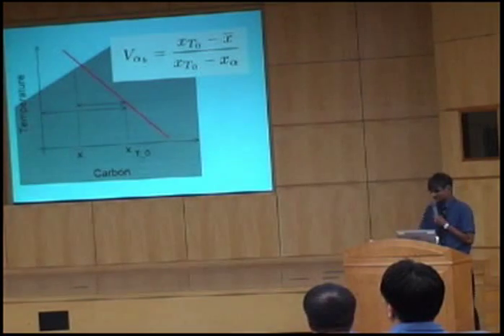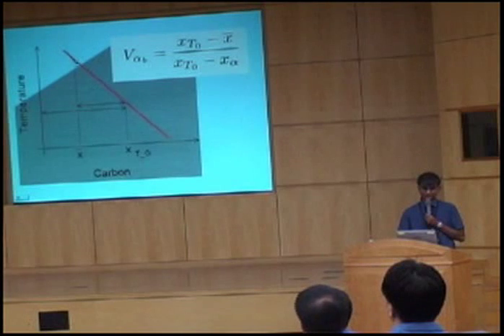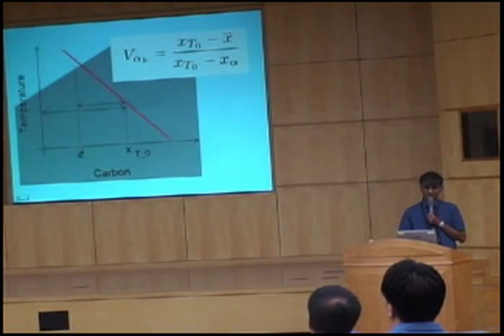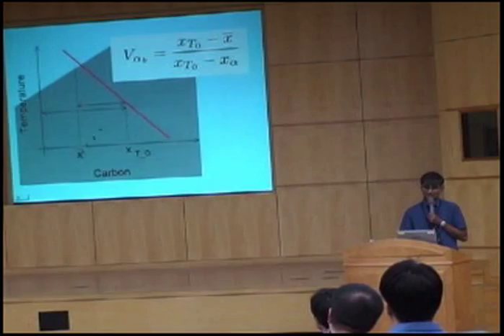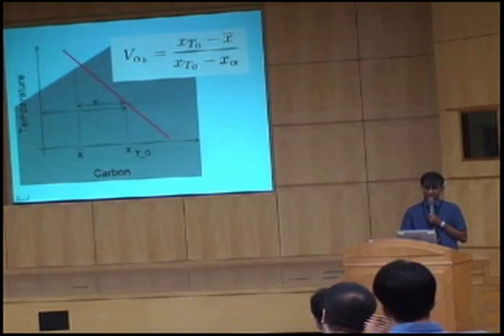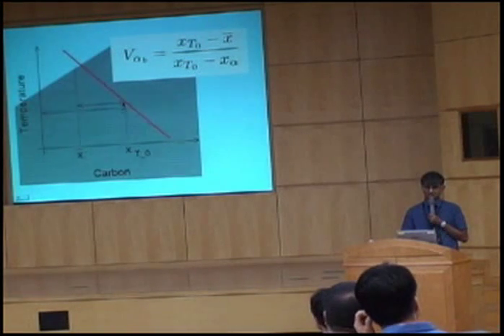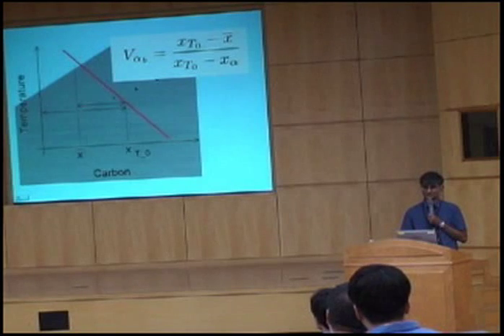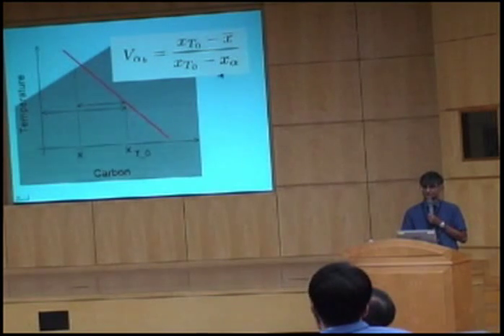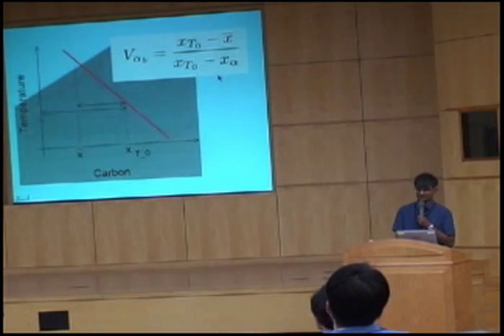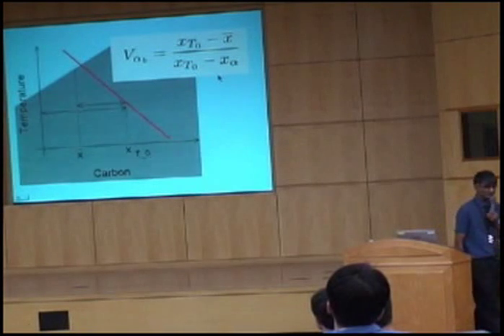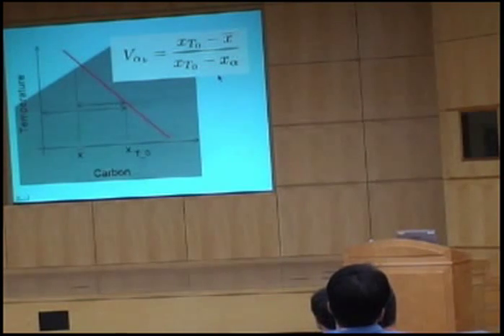So, this is our T0 curve here. This is the average composition of our steel, okay, in terms of carbon. And the volume fraction of bainite that we can get is given by this distance divided by this distance, because you can take the carbon concentration of ferrite to be zero. Okay? Solubility of carbon in ferrite is almost zero.